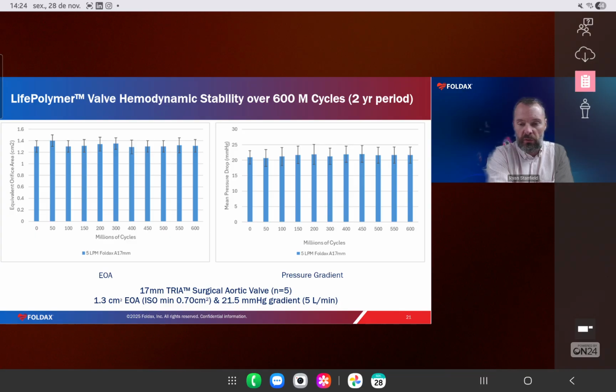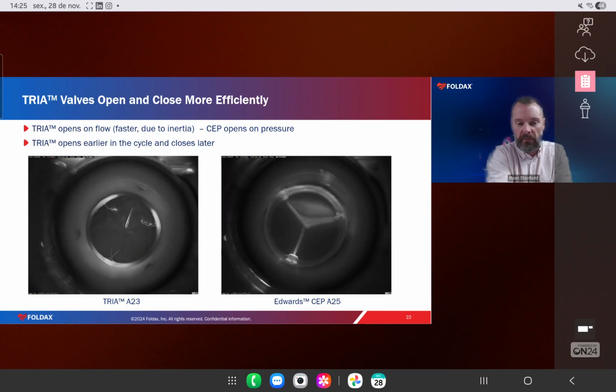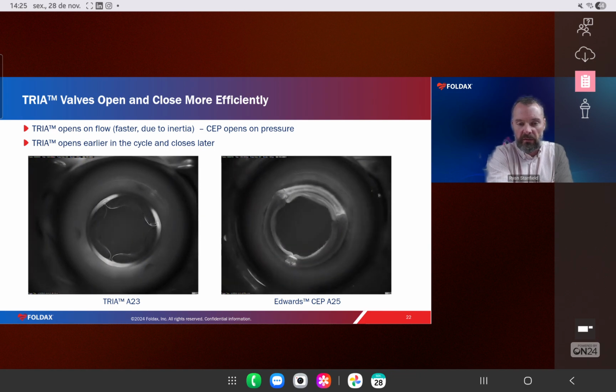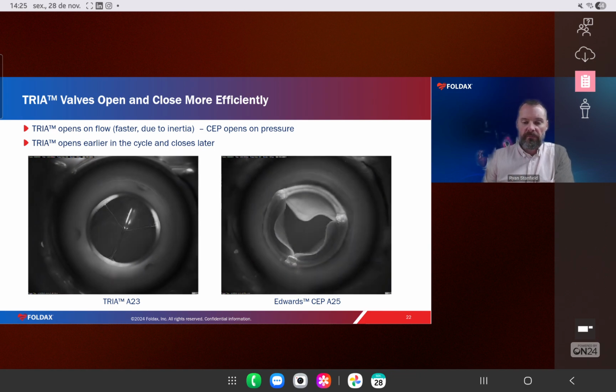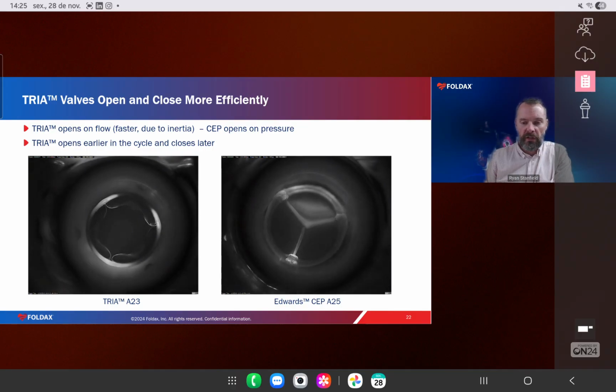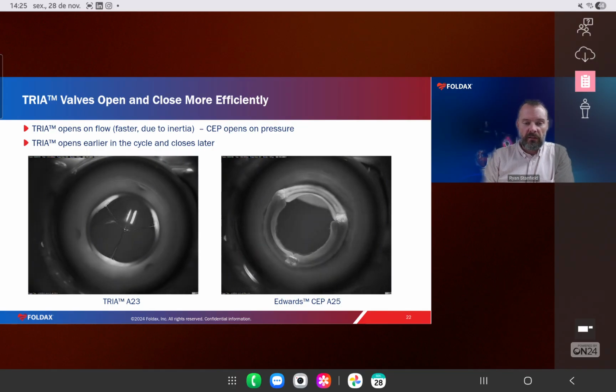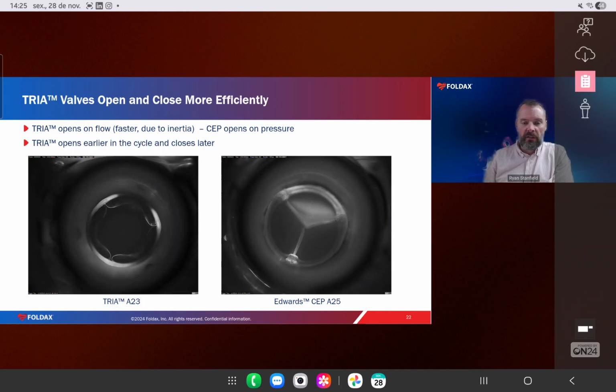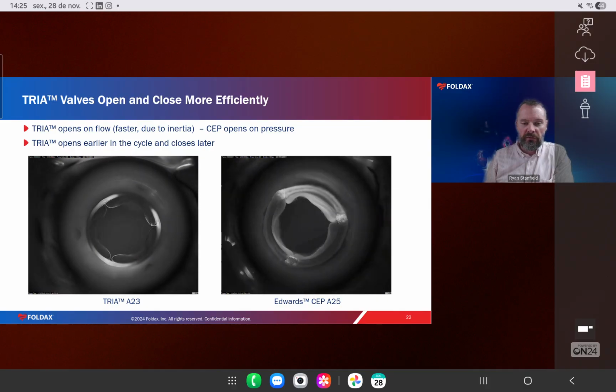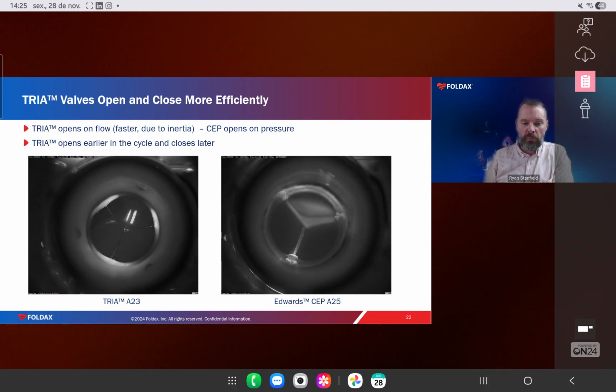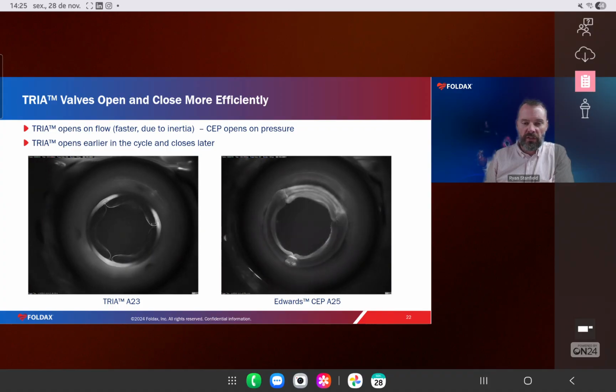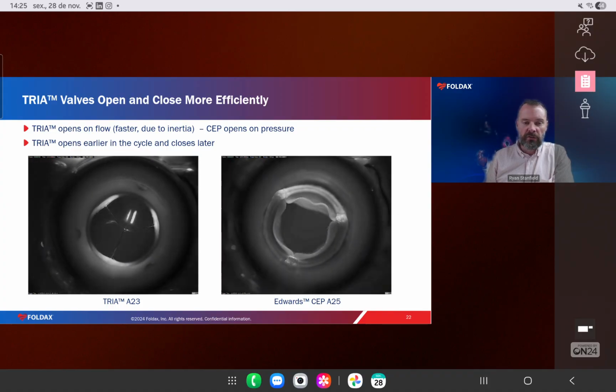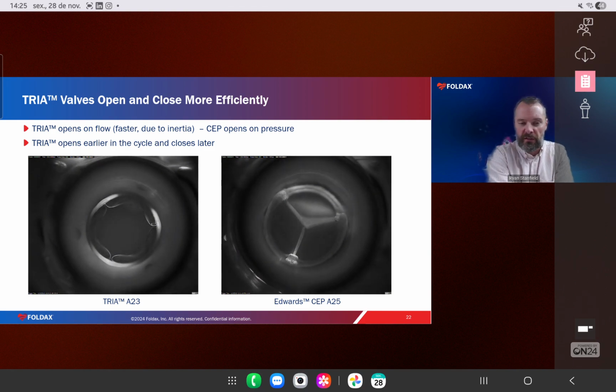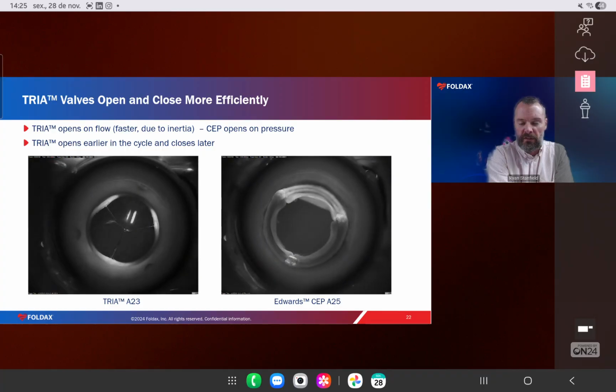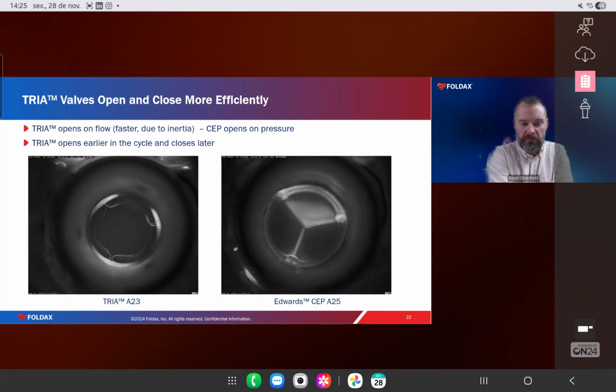And so, when we look at it and compare it side by side, this is compared to the Edwards tissue valve that you see on the right, and the Foldax Tria valve on the left. You'll see how stable the leaflets are in the polymer valve as the valve is opening and becomes fully open in a round configuration, and then quickly closes. So if you run these side by side, there are differences, and you look at it with the timer, there are differences in how long each one is open under the same conditions.